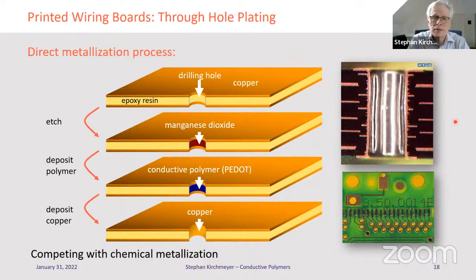The direct metallization process is still used and approximately has 20% of the market, while 80% of the market is still working with palladium. What's happening is this through-hole plating is usually done before the copper structure is developed on top of the printed wiring board. First step is drilling holes, and the holes are then exposing the epoxy resin to the next bath.